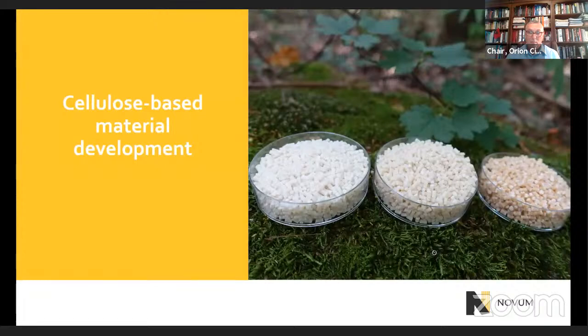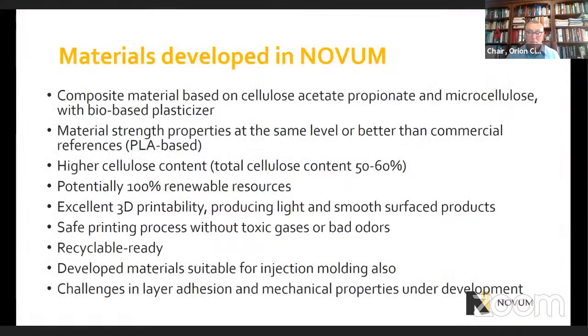So first, a few words about the cellulose-based material development. The materials developed in Novum thus far, we have developed roughly 30 different compositions. And these composite materials are based on cellulose acetate propionate and microcellulose, with a small amount of bio-based plasticizer if needed. And the material strength properties are at the same level or even better than the commercial references, which are usually PLA-based. And in our material compositions, PLA is not used. They have a higher cellulose content compared to commercial references, so we can reach the total cellulose content of around 50 to 60. And they are potentially 100% from renewable resources, so no fossil-based materials used here.